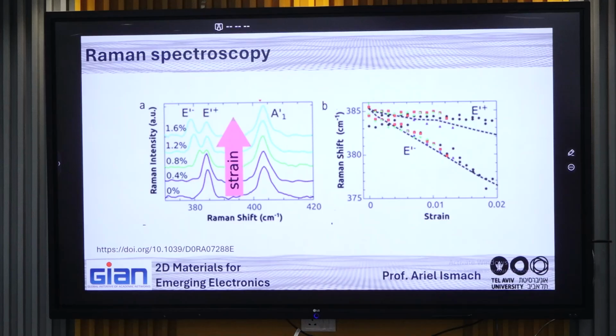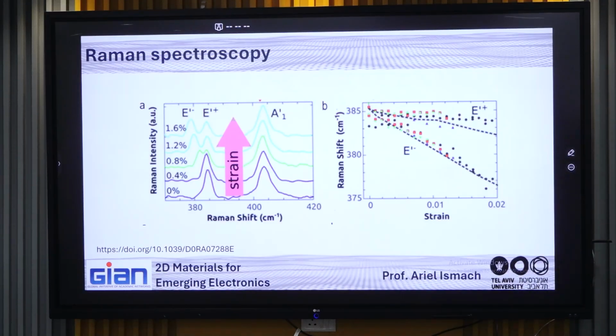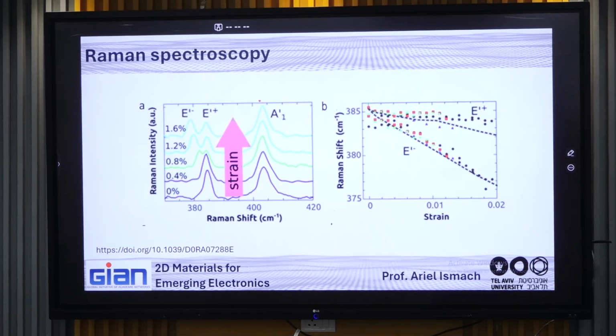There is one material that Raman is not so useful for. This one is hexagonal boron nitride. Hexagonal boron nitride, I forgot to add this. Hexagonal boron nitride has one peak in the range of 1365. One peak, only one peak.